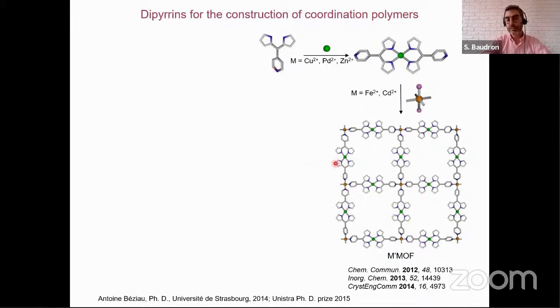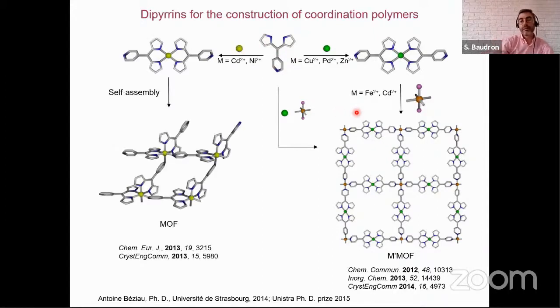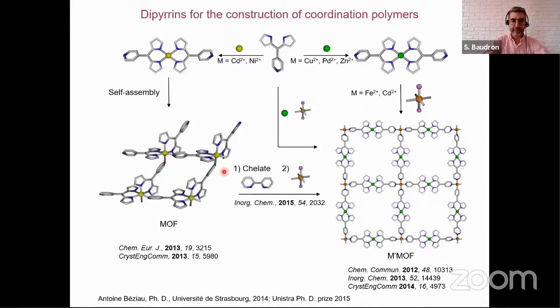Interestingly, the formation of such networks can also be done not only in a stepwise fashion, but also in a one-pot mode by mixing the ligand with a combination of those 2 metal salts. You have a selection of copper, palladium, or zinc for the dipyrrinato fragment, while the pyridine coordinates either iron-2 or cadmium-2. When the first step is done with cadmium-2 or nickel-2, we have a formation of complexes that tend to increase their coordination number, going from 4 to 6, leading to self-assembly and the formation of homometallic coordination polymers. Interestingly, those coordination polymers can be disassembled and reassembled into another architecture by playing with a chelate effect.